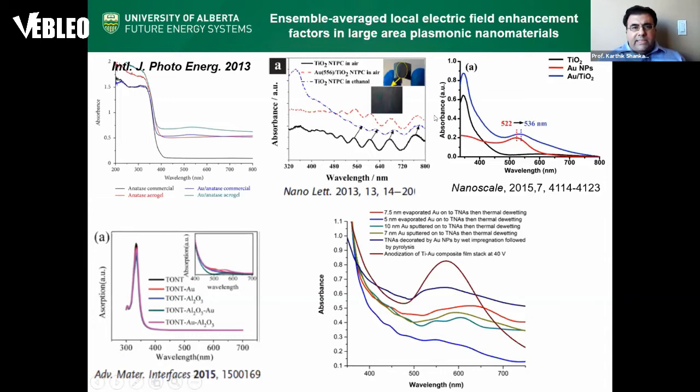One problem with this is that the high quality factors that you see in individual gold nanoparticles or lithographically defined ensembles of gold nanoparticles, you don't get to see those. So you see the plasmon resonances here are weak. In some cases, they are barely discernible. So what we did is we found a way to embed plasmonic nanoparticles inside the structures, because that helps not only with energy conservation, but also with momentum conservation. And that immediately allows us to get much stronger resonances. Resonances that have a higher quality factor, but also have a high oscillator strength.